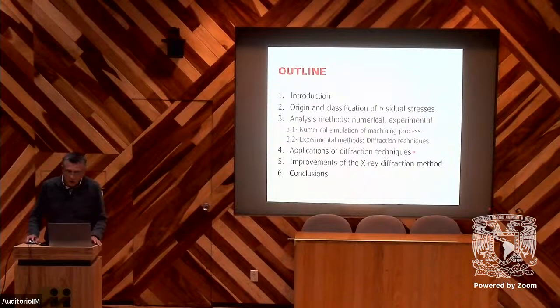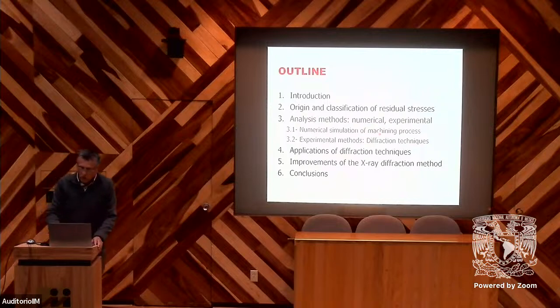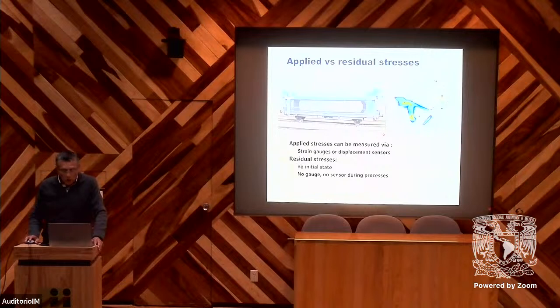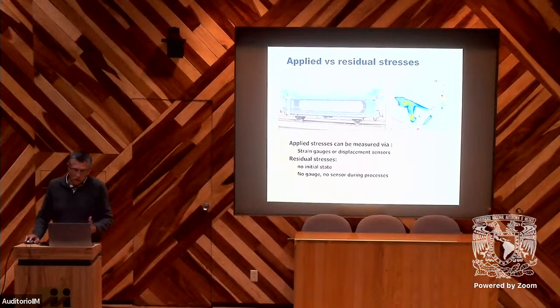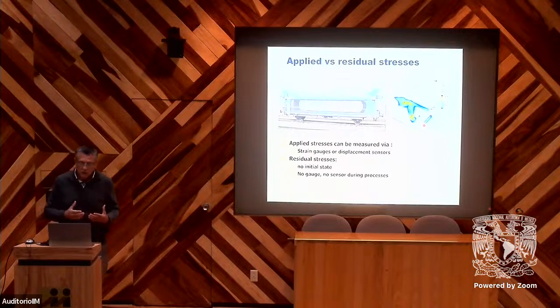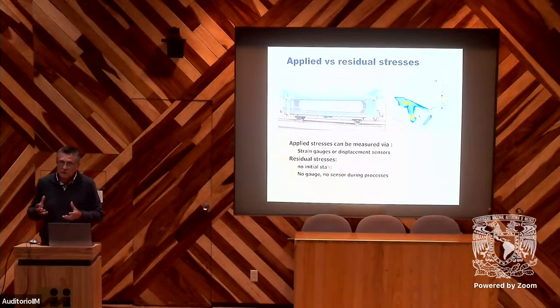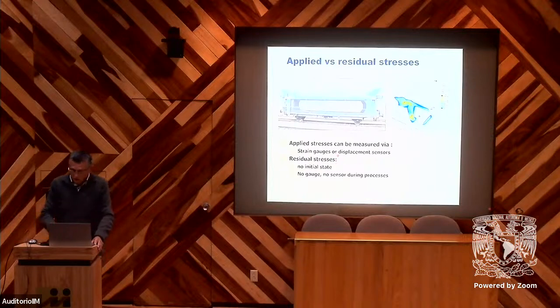So we can see now the methods to analyze residual stresses, and I will start with an example of a study using the finite element method to simulate a machining process. If we want to take into account the applied stress for design or sizing, it can be easy. We have methods to calculate this, but the problem is if we need to take into account residual stresses, we don't have strain gauges or sensors. We don't have the initial state, so it's complicated to analyze these residual stresses and to take them into account in our calculation or sizing.